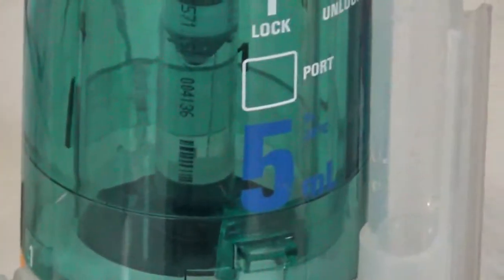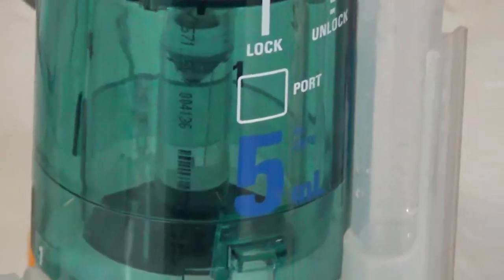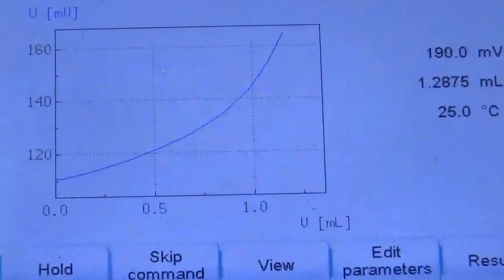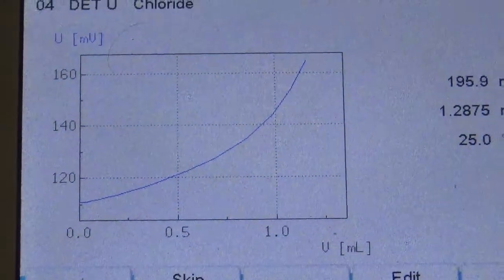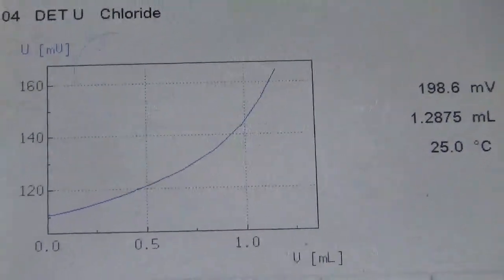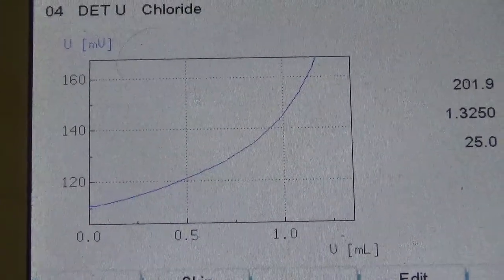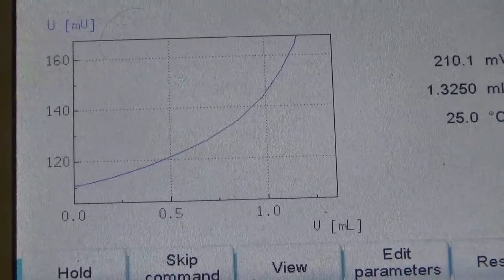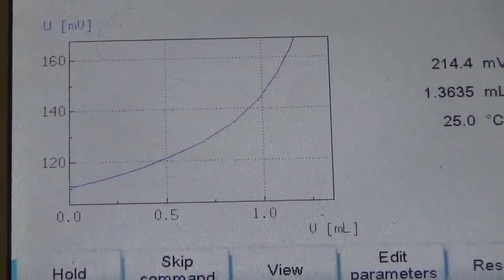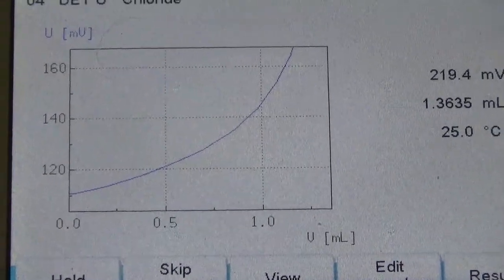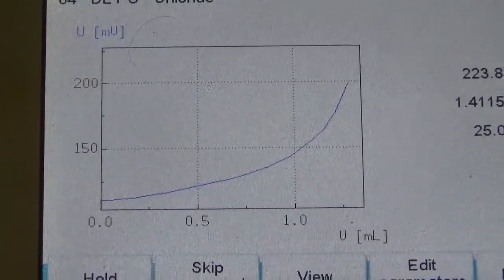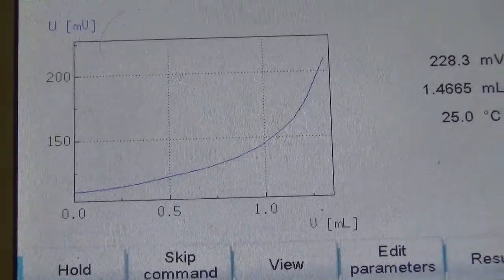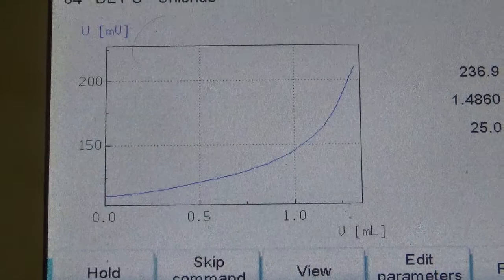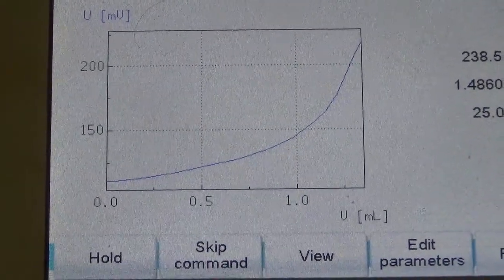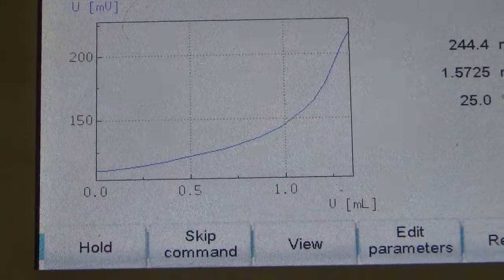Very precise dosing. And when the equivalence point approaches, titration slows down. The steepest point in the plot represents the equivalence point. Once the equivalence point is obtained, chloride content is determined according to the procedures of ASTM C1152 and C1218, which is basically a formula of 0.177 times equivalence point divided by sample weight.